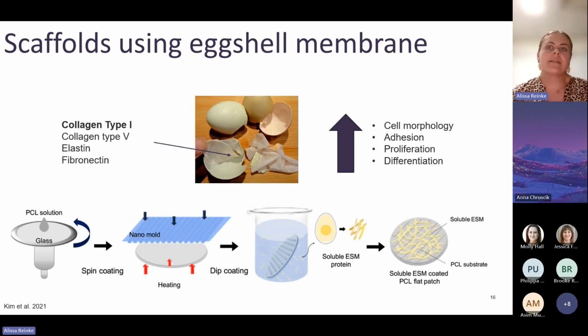Now, from that point, literature suggested that we would need to coat the scaffold in a membrane or some kind of extracellular matrix to allow cell adhesion. So, keeping in the theme of using eggs and waste products, I created an eggshell membrane solution. That is the eggshell membrane on the inside of an eggshell, and it's very high in a number of different proteins, primarily collagen type 1, but it also has collagen type 5, elastin, and fibronectin, and all of these are proteins commonly used to improve cell adhesion. So the use of this should improve cell morphology, adhesion, proliferation, and differentiation, which are all things that you want when you are doing cell culture research.